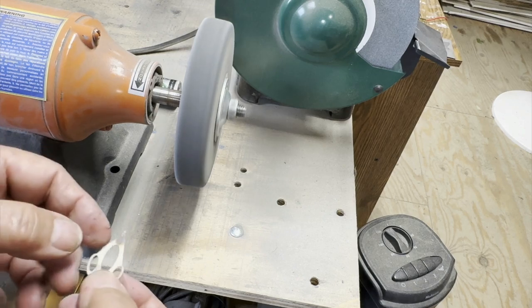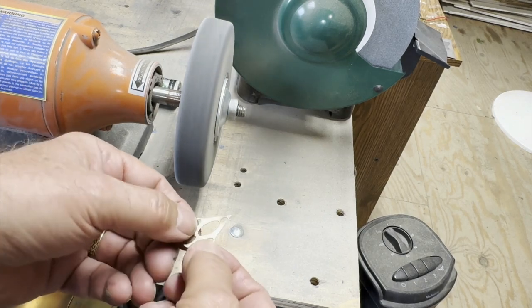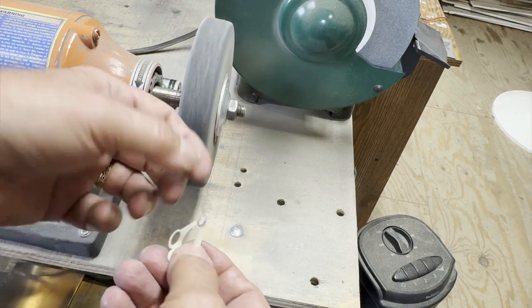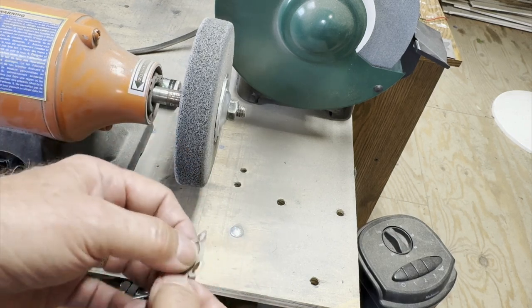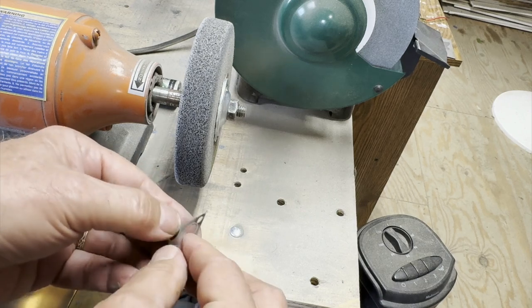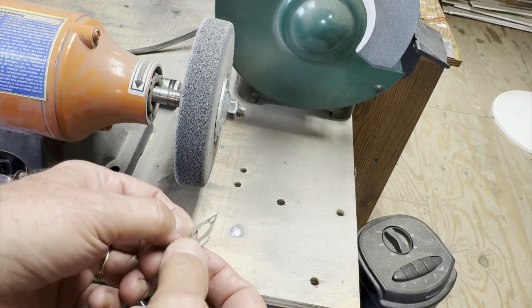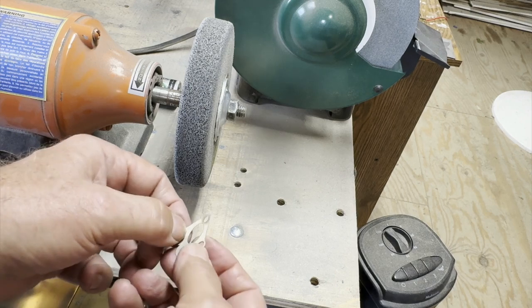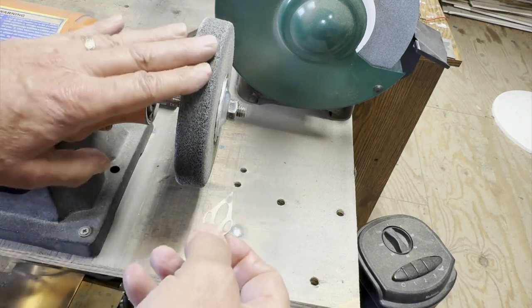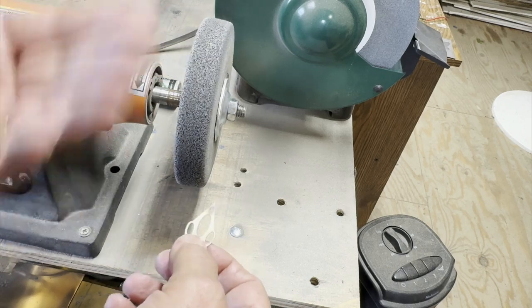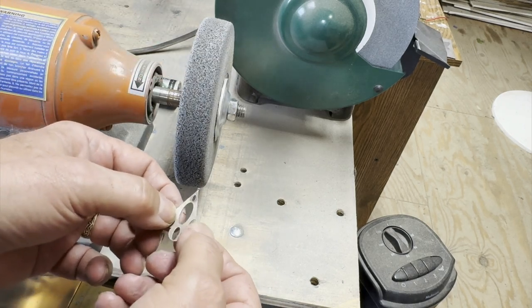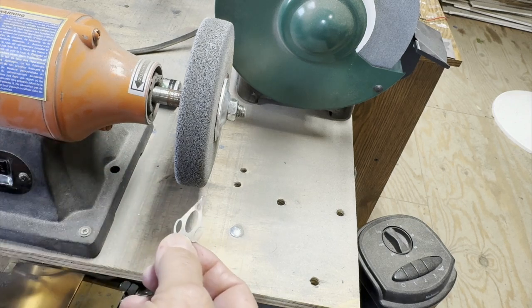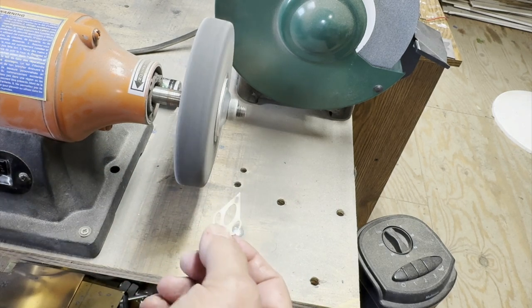One thing you're going to want to do is to sand or lightly polish your titanium, because no matter how fast you go it's going to heat up and it's going to discolor. It will help your predictability of what you're going to color it with if you can get the surface at least back to bare metal. I'm using a buffing wheel with a scotch-bright pad; you can use anything really—sandpaper, fine steel wool, something like that. This is just what I do because it's really easy.